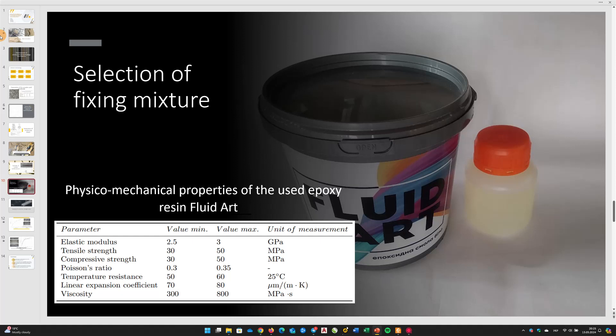The application of the mixture in the groove was done in several stages. Initially, the empty groove was filled with resin to a depth of 1 third. Then the dowel was placed in it, and it was covered with resin to completely fill the groove. The spatula was used to distribute the resin in the groove and clean up excess. After completing the preparatory work, the blanks were kept for 40 minutes, working time of epoxy resin.